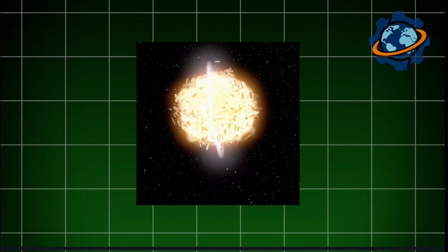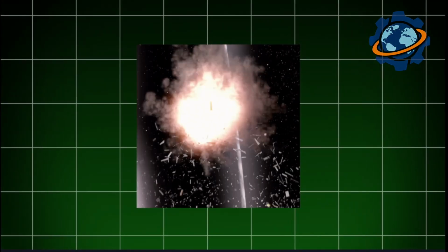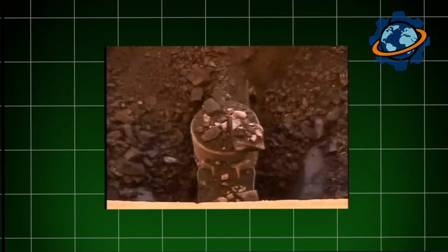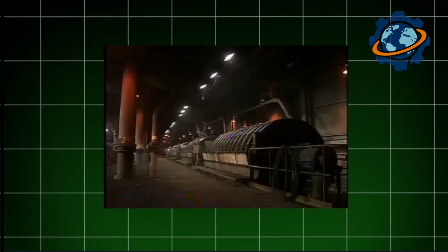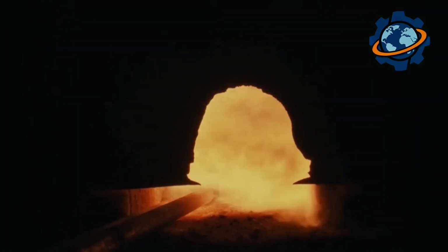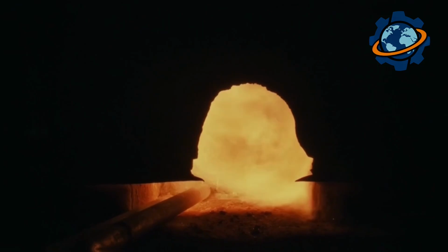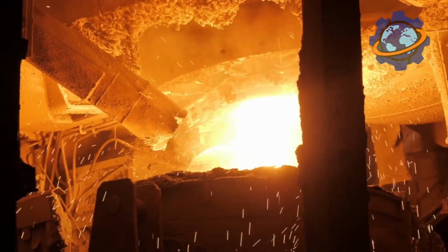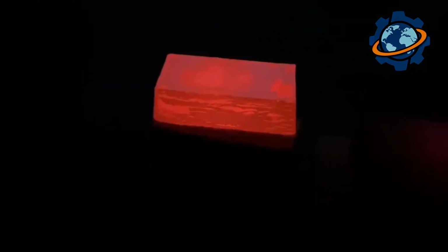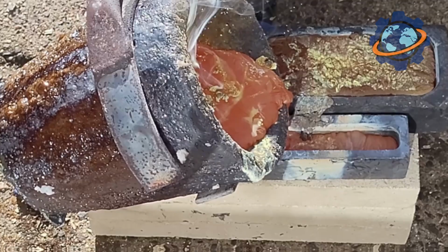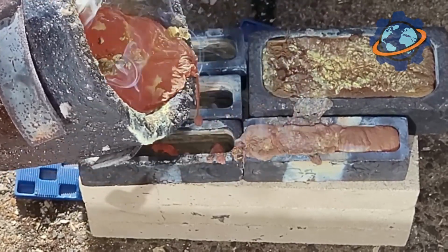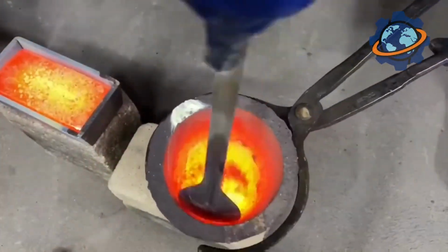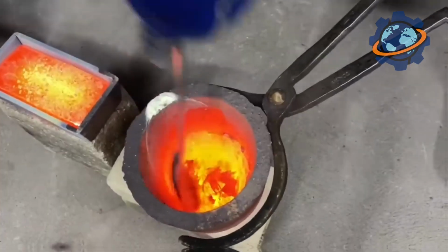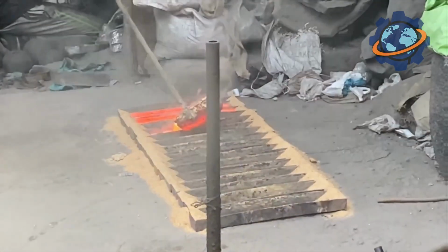And so, having traveled from explosions a mile deep through giant crushers and flotation tanks, through fluid bed furnaces at 1,650 degrees and retort towers at 2,200, through transformation into metallic vapor and condensation, zinc emerges, the bodyguard metal of modern civilization. The silvery metal that sacrifices itself, protecting steel from rust, the fourth largest metal by production on the planet, without which all infrastructure would collapse.